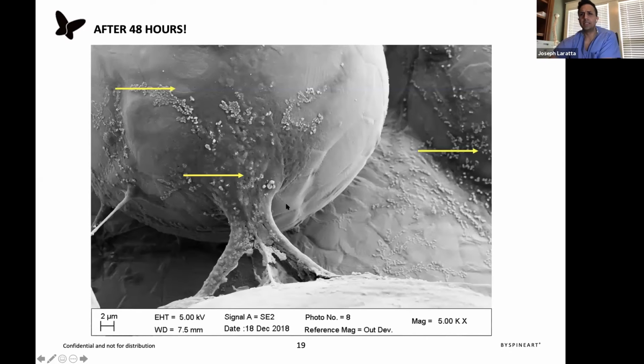And this is a really interesting slide that shows the scanning electron microscopy after 48 hours of inoculation of the stem cells on the TiLife technology. These dots are the cells, and these big globes are the metal struts. And you can see that there is extracellular matrix already extending between the metal that's being excreted by these cells as early as 2 days after deposition of the cells. So there's early cell-to-cell communication in addition to adherence on this type of trabecular biomimetic metal.